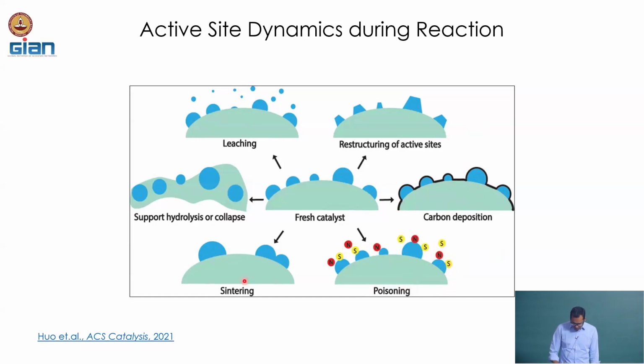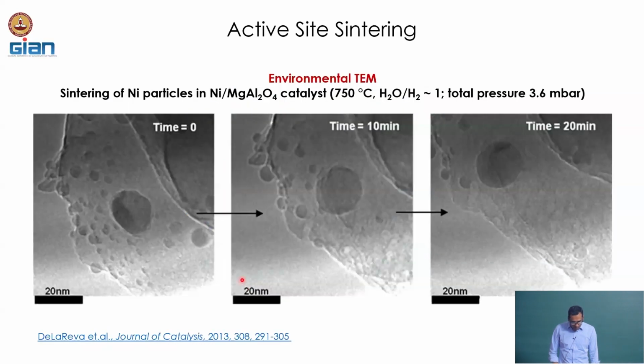Now, let us look at one example of sintering. Here is a time-resolved environmental TEM image of a catalyst where nickel is deposited on magnesium aluminate, and we are looking at the catalyst structure evolution at 750 degrees Celsius in a typical hydrogen to water ratio of 1. Since the TEM experiments are conducted under vacuum, the pressure here is about 3.6 millibar. What we see is that at time 0, we have a couple of bigger nickel particles, but we also have a bunch of smaller nickel particles present.